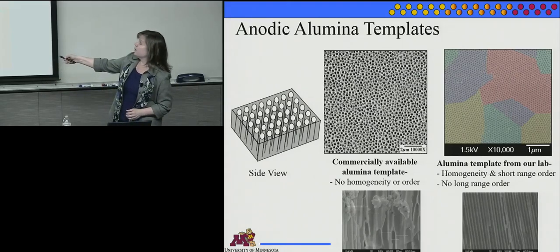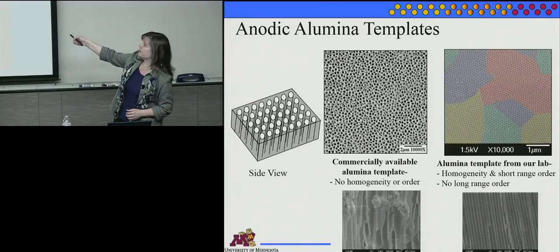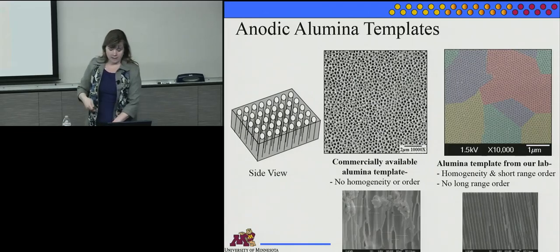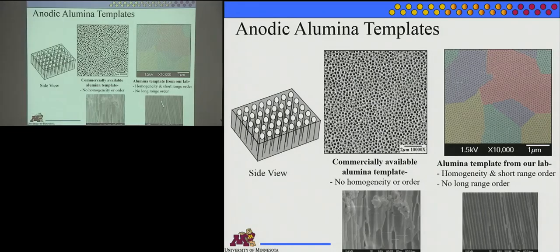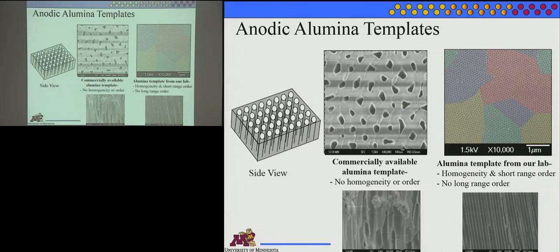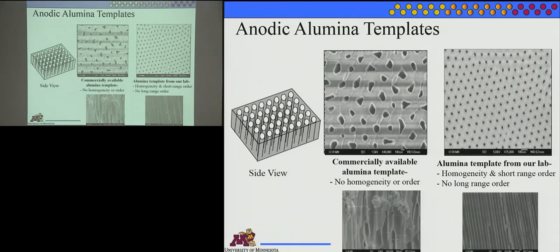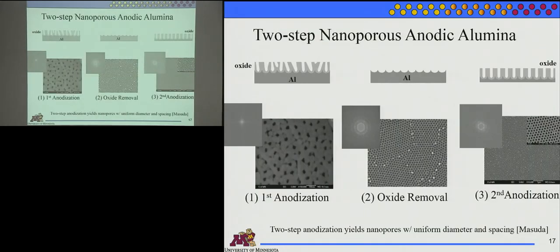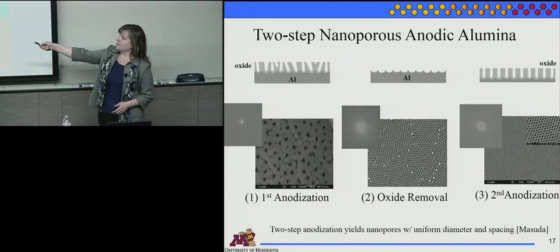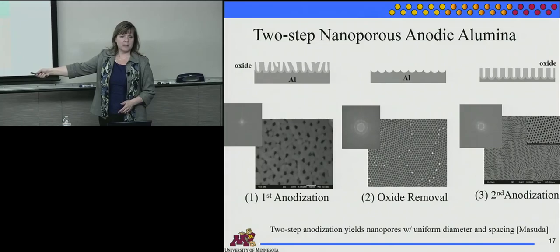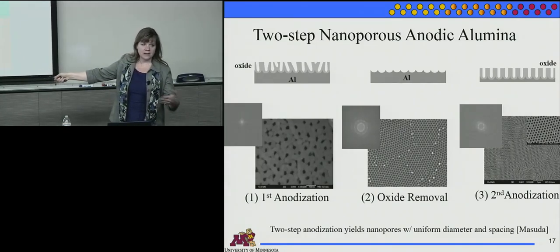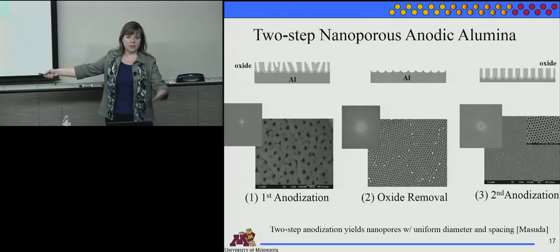So if you were to follow one row of pores, you see that it goes off to a distance. So it's almost like grain boundaries. But the sidewalls are very smooth for the entire growth. If you zoom up, you can see they're very uniform. So how do you do those? Well, here's my aluminum, and I'm oxidizing. And from the beginning, the oxide looks pretty bad. It just finds a minimum in the substrate, starts to form a pore. As it's oxidizing, these pores grow.